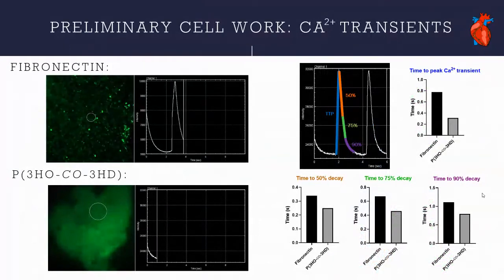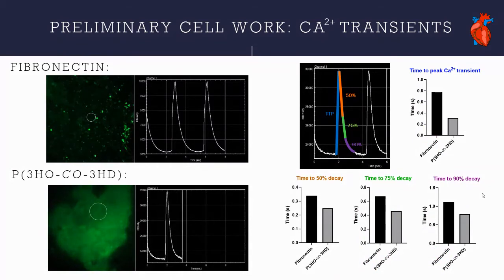Further to this, I've also looked at calcium transients. So loading these cells with Fluo-4 shows us how the calcium moves through a monolayer of cells and shows us the beat rate. And whilst more experiments of this need to be done to get statistical data, so far it's looking as though the heart rate is a little quicker on my polymer samples.